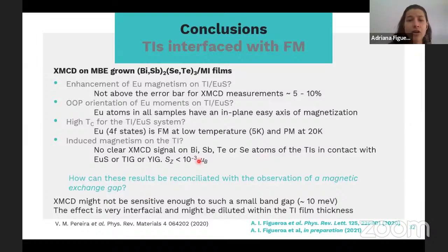And well, there are some ideas of what could happen. How can these results be reconciled with the observation of a magnetic exchange gap that is observed in magnetotransport measurements? It could be related to the sensitivity of the XMCD to small gaps, and there are other ideas that say that, since these proximity effects are very interfacial, they might be diluted within the TI film thickness in these X-ray absorption spectroscopy